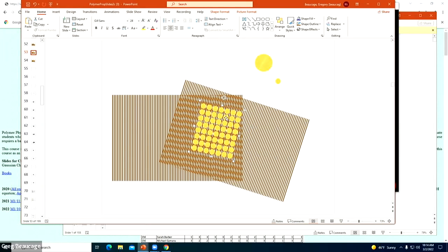So that's the basic beginning problem. You won't get any diffraction out of it. It isn't like a microscope where you see it; you only see it when it's lined up right. There are two ways around that. You could take the diamond ring and grind it into a powder. Then you would have all possible arrangements of the crystal, and you would get a diffraction pattern from it. That's called a powder pattern.